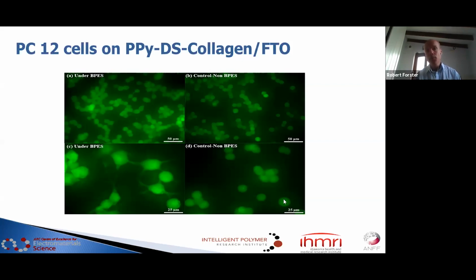If the cells are left without stimulation for 7 days, you can see there's still a significant population of viable cells on the surface. But very significantly, with the wireless electrical stimulation, the cells are still alive, still actively growing on the surface, and very significantly, they have differentiated into nerve cells.